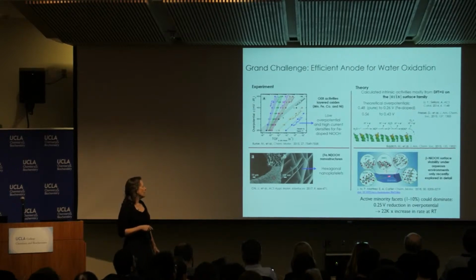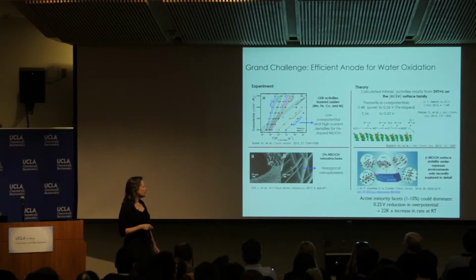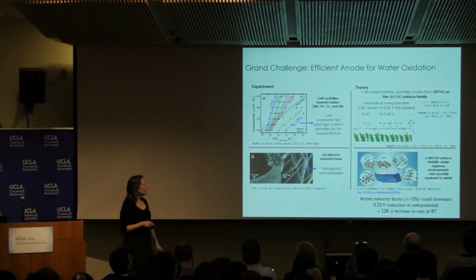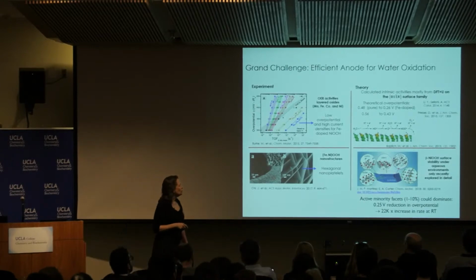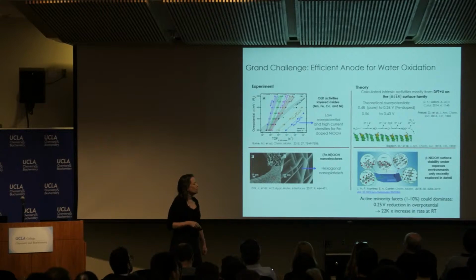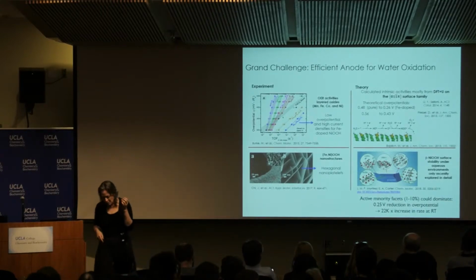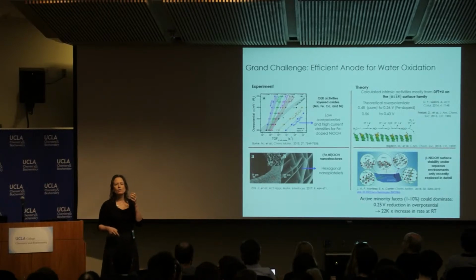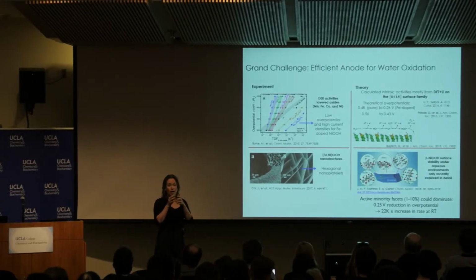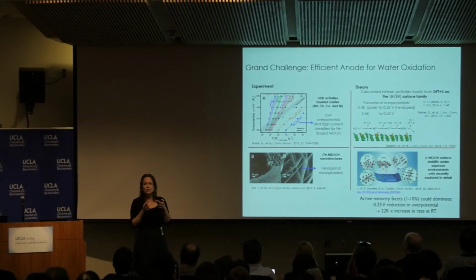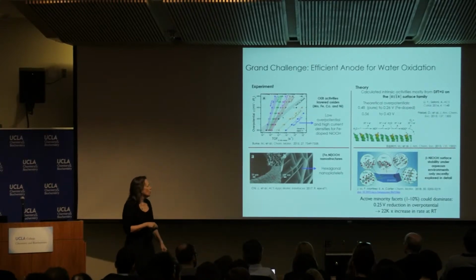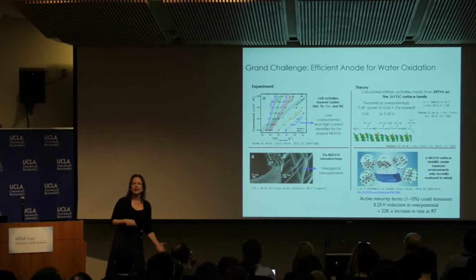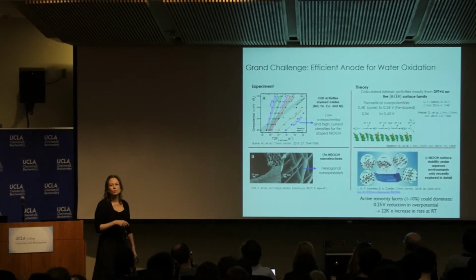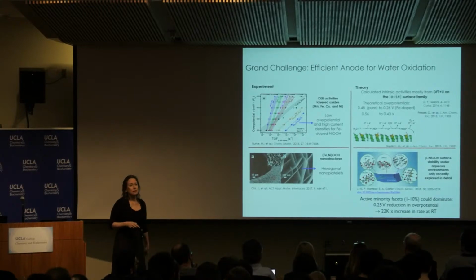Bottom line is we then did a bunch of work looking at the dominant facet, which is the basal plane, but also looking at a facet that had not been looked at at all, that is a minority facet, but it has enough low coordination iron, when it's doped with iron, or low coordination nickel, that we thought that it could in fact play an important role. Because as we know, if you have a coordinatively unsaturated metal, that tends to be more reactive. And so even if we could see a reduction in the overpotential of a quarter of a volt, that could lead to over a 10,000, 20,000 fold increase in the rate at room temperature. So even small changes in that overpotential make a big difference.